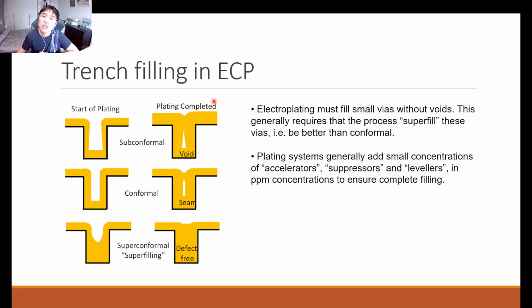Okay? So it generally requires that this process is better than conformal, because with conformal or sub-conformal plating, you tend to leave seams and voids in the middle of the vias and trenches. However, if you use a super conformal, also known as super filling, recipe that's able to achieve that, we can obtain a defect-free filling of the high aspect ratio trenches and vias. To achieve that, we generally modify the electrolyte by adding chemicals known as accelerators, suppressors, and levelers in very small concentrations to allow the right profile of electrochemical plating.